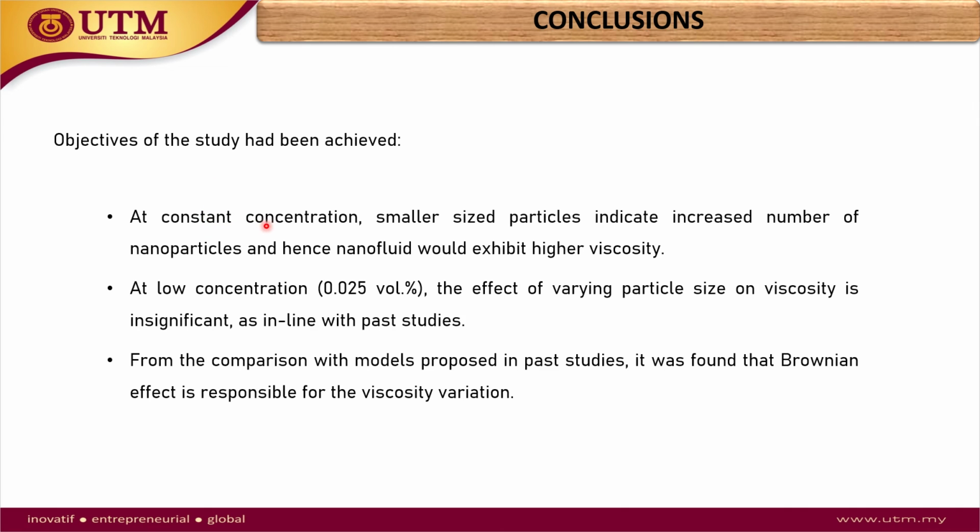At constant concentration, smaller size particles, which means an increased number of nanoparticles, will exhibit higher viscosity than base fluid. At low concentration, the effect of different particle size on viscosity is minimal. This is the same as those past studies. And from our comparison with the models in past studies, it was found that Brownian motion is also responsible for the viscosity change. That's all from my presentation.